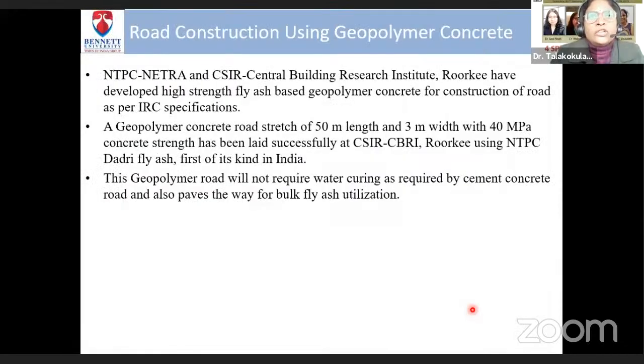If you look into the field application part of this geopolymer concrete, very recently NTPC, NETRA and CSIR, Roorkee, they have developed high strength fly ash based geopolymer concrete for the construction of road pavement, which has been laid for a stretch of around 50 meters length and 3 meter wide with 40 MPa GPC as per the IRC specifications.